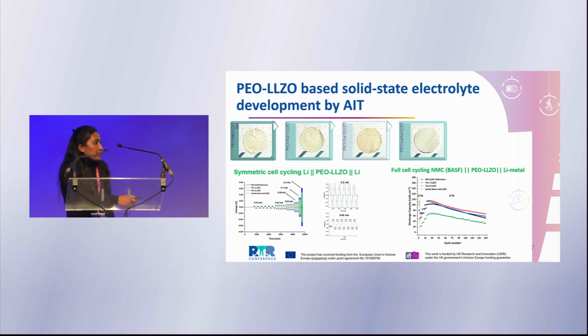And so, as my colleagues can agree, in solid-state electrolyte batteries it is very important to form the percolation between the cathode and the electrolytes, because this is a very dry solid-state battery technology, and it is very challenging to form the interfacial stability between the cathode and the electrolyte materials. So we first cycled these cells with lithium, with different lithium plating and stripping, to understand the stability of this particular electrolyte with the lithium metal.